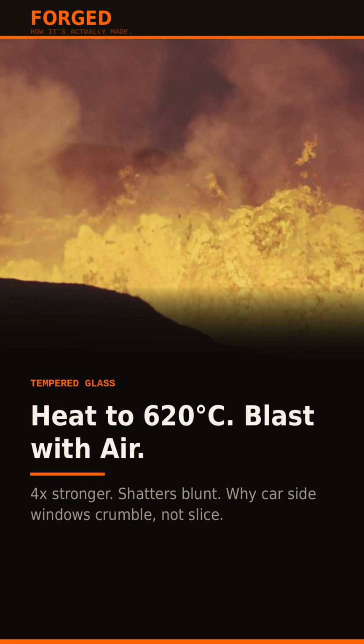Tempered glass, used in car side windows, shower doors, and phone screens, is made by heating the annealed glass back to around 620 degrees and then blasting it with jets of cold air. The rapid cooling creates a surface under compression and an interior under tension. This stress makes tempered glass roughly 4 times stronger than ordinary glass, and when it does break, it shatters into small blunt pieces rather than large sharp shards. That is why your car's side windows crumble instead of slice.